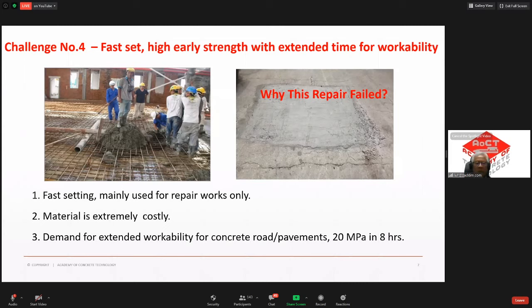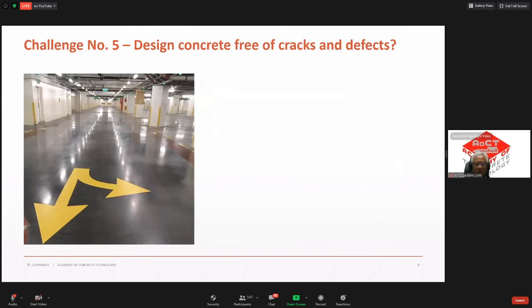So challenge number 5, the final one, is actually to design concrete free of cracks and defects, which is very, very a real challenge. It's not easy, right? Like us as a floor specialist, we have been looking into a lot of solutions. We try a lot of materials, and finally we are almost there, right? So try to use as low water cement ratio as possible, right? And you all know very well that if you don't have enough water, you also will cause autogenous shrinkage crack.